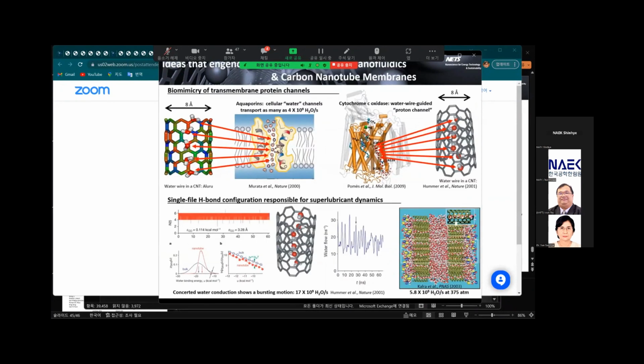The pioneers of carbon nanofluidics had a mindset that the carbon nanotube interior could mimic biological transmembrane channels for water and ions. It is known that water molecules can spontaneously fill the carbon nanotube interiors by adjusting their hydrogen bonding network. When the carbon nanotube diameter shrinks to sub-nanometers, in particular, they can even configure themselves into a single file, gaining an additional degree of freedom.